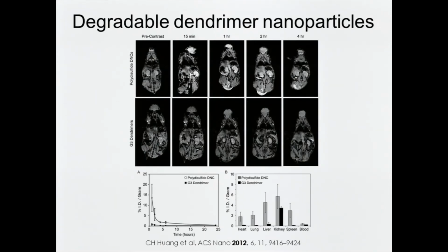And what the biodistribution tells you is that it's pretty well excreted, because, say, a G4 dendrimer would probably have a liver uptake of 30-40% at this time point. So, although there's still some retained in the animal, it's pretty good excretion.